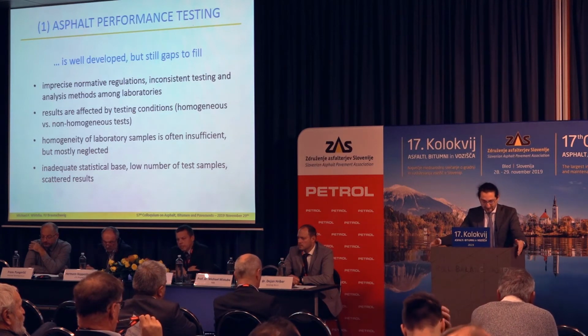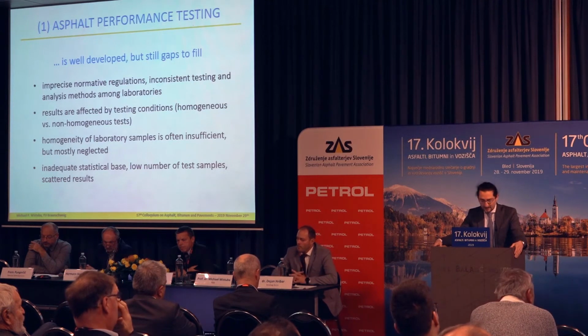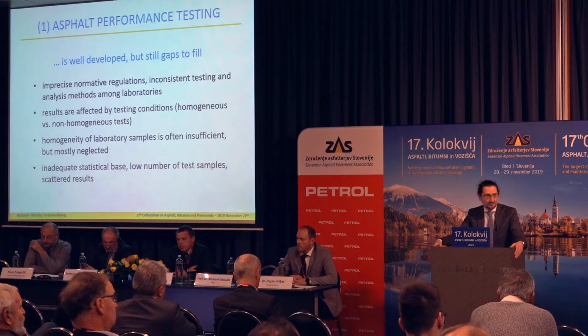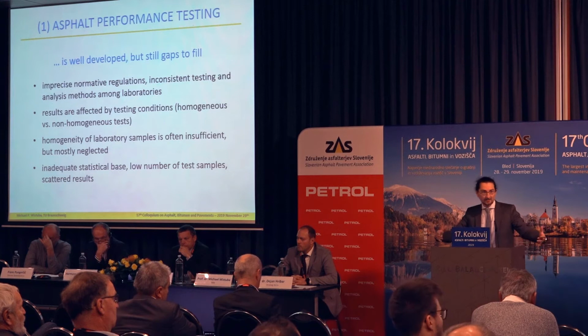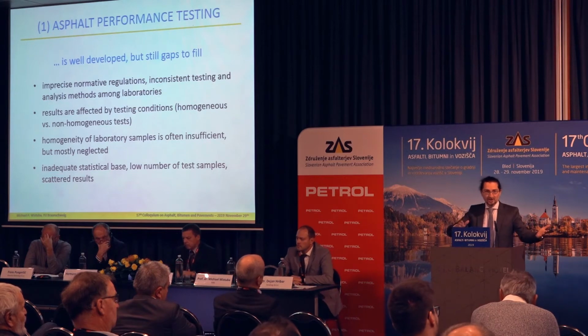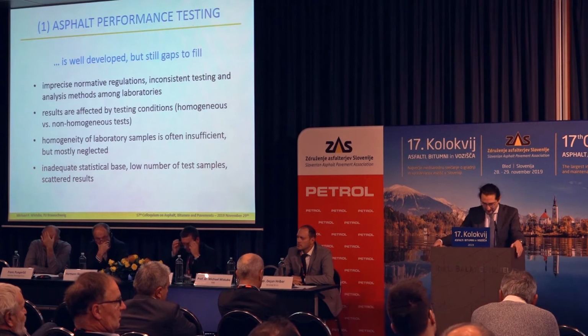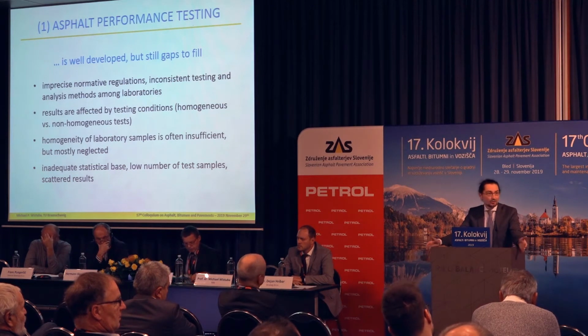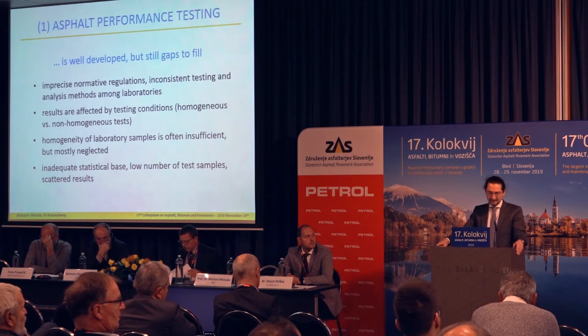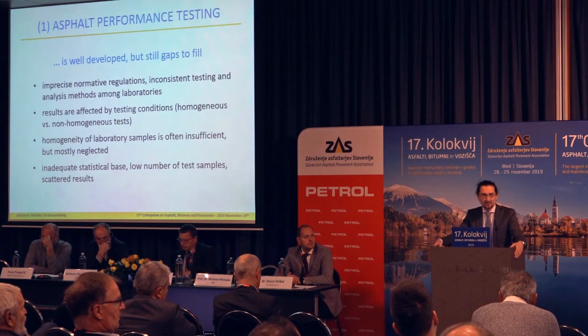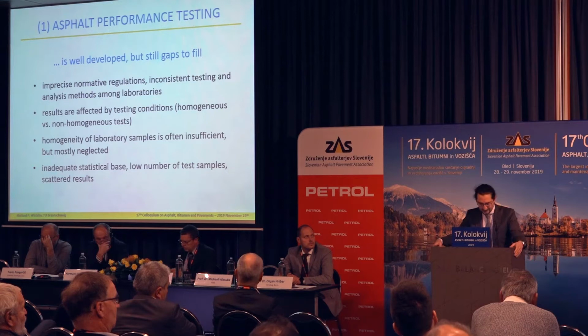So we have troubles. Another example why there are still gaps to fill is that the results are affected by the testing conditions, by the geometry of the test specimen, by the shape of the test specimen, by the magnitude. There is a size factor which is not considered. And we try to separate homogeneous from non-homogeneous tests to make at least a rough distinction of tests. We ignore more or less that the samples are not homogeneous. And this inhomogeneity is insufficient and leads to rather big scatter in the results. So this is mostly neglected, even though we know about these influences.